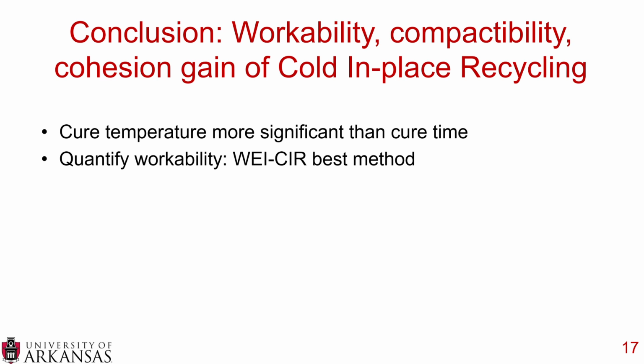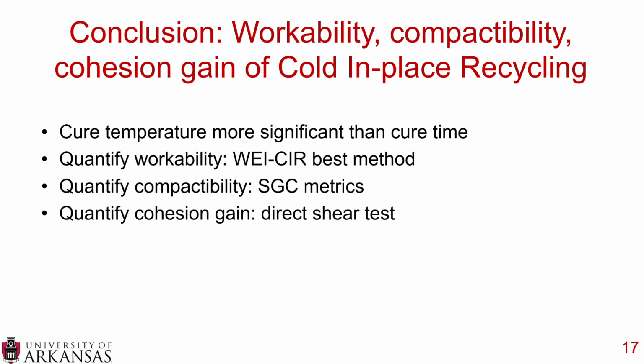We found that in general, the curing temperature was more significant than the curing time. In order to quantify workability, we recommend the WEI-CIR as the best method. In order to quantify compactability, we found that the superpave gyratory compaction metrics were the best way to go. And then in order to quantify cohesion gain, we really feel that there's a lot of promise with the direct shear test.